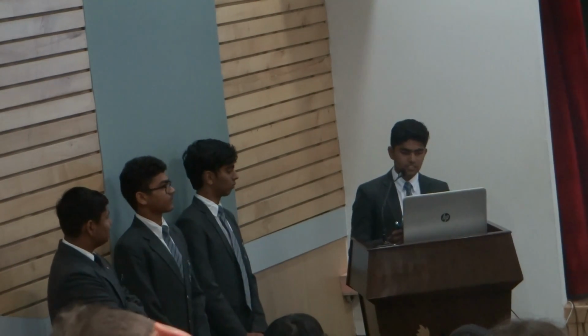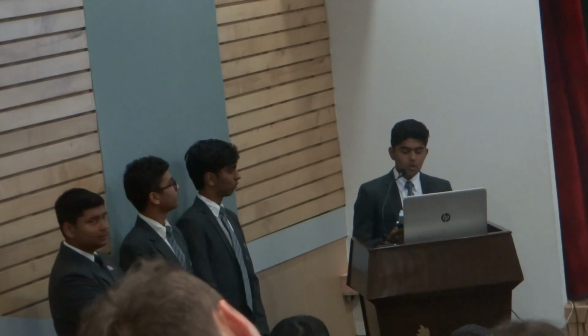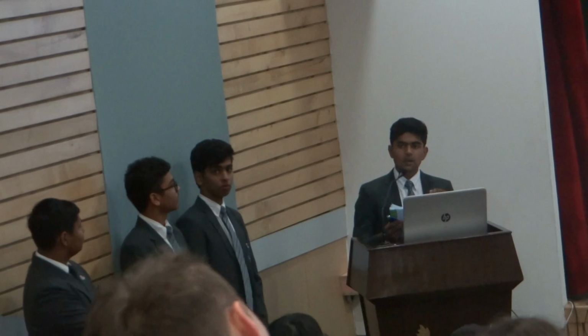First was with a molarity of 0.6, which is the green line right there, underneath the yellow of 0.8 and the blue of 1. Now we chose the molarity 0.6 because it produced the most effect of light in the experiment that we conducted in artificial light. Now, after the current had stabilized, we took our first reading, which was of a rate of 9.97 milliamperes. Within the next 10 minutes, it dropped by 1.33 milliamperes. Therefore, it had a drop percentage of 13.3%, which is pretty decent according to us.